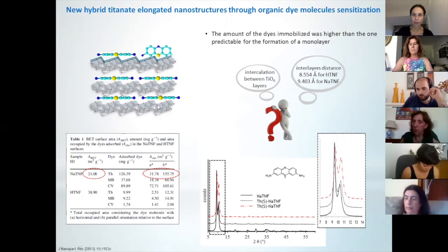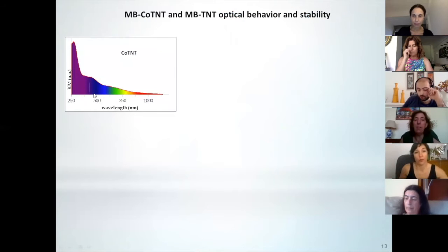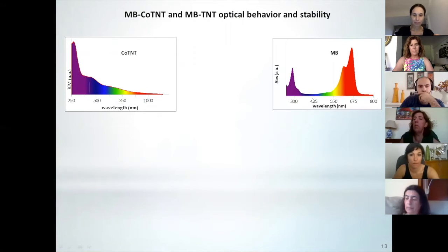So that's because this molecule is in the interlayers. Then we decide to combine these results with the doping. So we decide to modify titanate nanotubes doped with cobalt. We decide to put it in contact with methylene blue in this case.